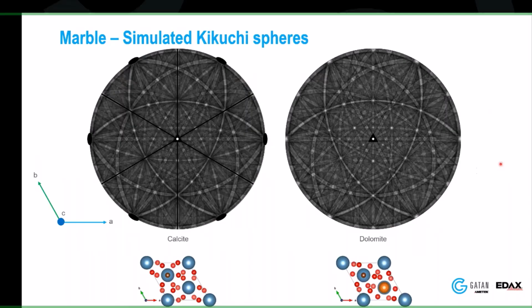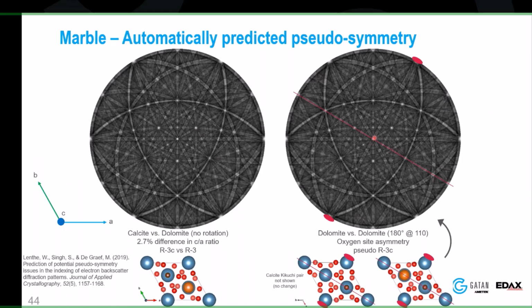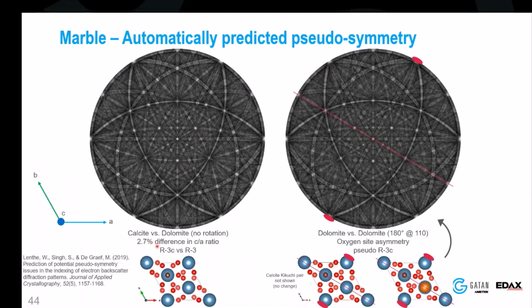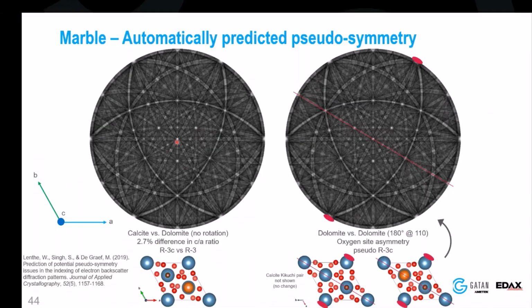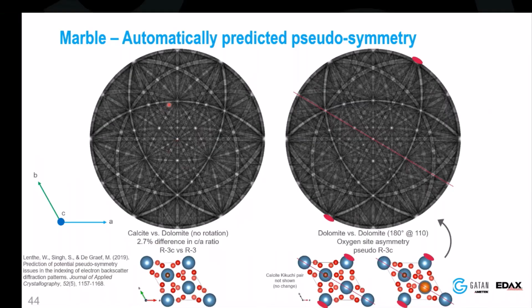And you start looking at these, you're going to have a lot of problems finding major differences. But luckily enough for us, the computer does see them. But here again, you can see the calcite. Here you can see the dolomite. And the nice thing about this is I can actually flash them back and forth. So over here on the left-hand side, you can see there's that 3% difference between the calcite and the dolomite. You can kind of see these very small differences here.